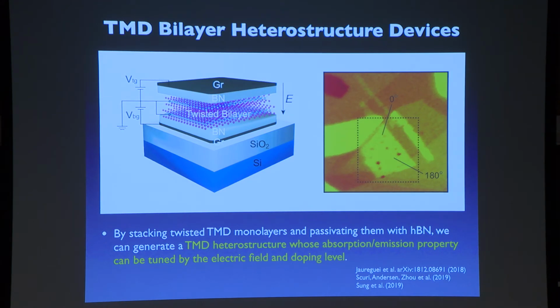So what we decided to do was to do optoelectronic characterizations of twisted bilayers made of the same materials, like tungsten diselenide, molybdenum diselenide, so that we can introduce as small a variable as possible. So the type of structure that we make is the following. We actually generate twisted bilayers. Basically, we put one layer down, twist a little bit, and another layer down, but they are made of the same materials. And then we add boron nitride on both sides so that we can protect them.